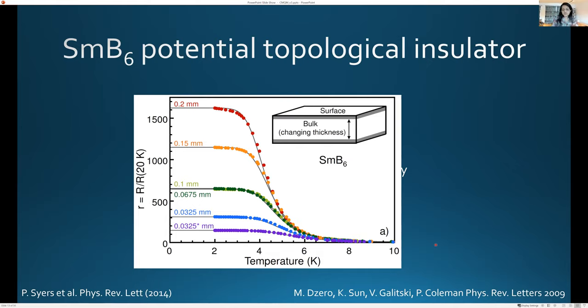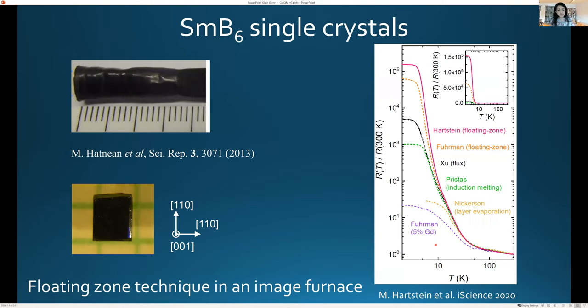So this is the reason we initially started studying this material, because we were curious about whether we could see the Fermi surface of the conducting physical surface of this material, which is distinct from the insulating bulk, which we would not expect to show a Fermi surface. So given that it's particularly important for the bulk to be an excellent insulator, we chose to study floating zone